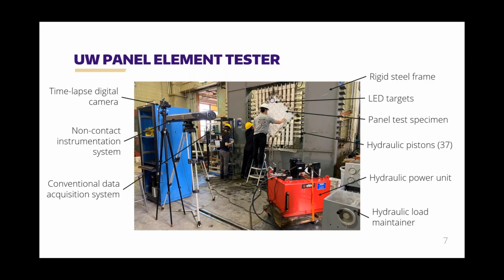So here you see the panel tester in our lab. You have a rigid steel frame, which is going to be used to react all of the loads. You have your panel test specimen there, which is the diamond-shaped specimen in the middle. We're applying an in-plane stress state using 37 hydraulic actuators, and those are all being controlled by a hydraulic load maintainer, a hydraulic power unit. So we're applying a state of known stress, and we can apply any state of in-plane stresses in terms of pure shear or shear plus axial, shear plus tension. And then we're measuring the strains using a non-contact instrumentation system, which is really just keeping track of the location of these LED targets that are applied to that front surface.